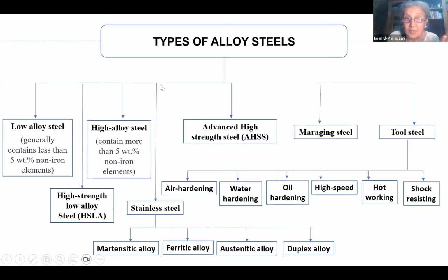Actually, during the last decades, we had some additions to this conventional family of alloyed steels, where we had, for example, the high strength low alloy steels. These were introduced something like 30 or 40 years ago. And the idea was just adding minor amounts of alloying elements, not as high as the 5%, but less, and we still can get higher strength, especially for construction applications. Not only that, we had other advances that have appeared and are still having research currently, like the advanced high strength steels. And these are special tailored groups of steels based on the conventional groups, but we tailor their properties by other methods apart from alloying elements, just like the heat treatment, for example.